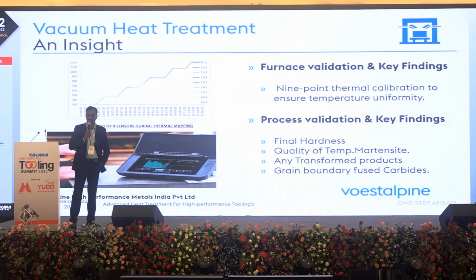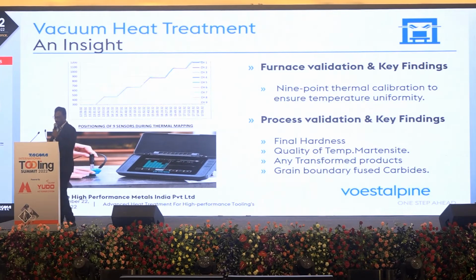So we need to ensure that the thermal hot box is completely uniform in all perspectives. Of course, there is certain process validation. Different grades of materials are going to be heat treated, for cold work tool steels and high-speed steels, which have different alloy chemistries. So the final hardness is very important, and we qualify through the final hardness and the quality of tempered martensite.